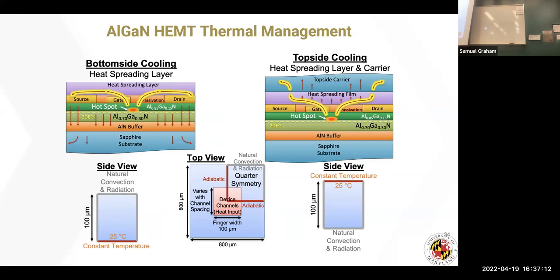So one of the things that we would like to be able to do is spread the heat. So I can place a heat spreader on top. And so this is a dielectric layer, a heat spreader. And then the other thing that I could do is the top side, the flip chip bonding, where I pull the heat out through the top. So there are a couple of different things that you can do. So this is sort of the normal packaging. So remember, I'll just point out that sapphire has a very, very low thermal conductivity. It's not great. And so the question is, if I just put a heat spreading layer on top, can I actually help and get away with the thermal management for these kinds of devices?